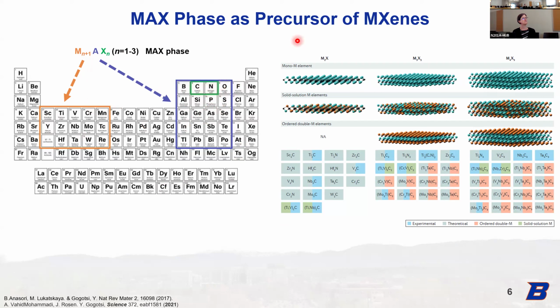So, you can see some of the different types of MXenes that have been realized from the 2-1 ratio, 3-2, 4-3, and more recently the 5-4 has been synthesized. And you can see you can get different solid solutions in the transition metal, different layer ordering. So that's like a lot of the 2D family, right? A lot of interesting things to explore within the MXene family, the structure and how that affects their properties for these different applications.